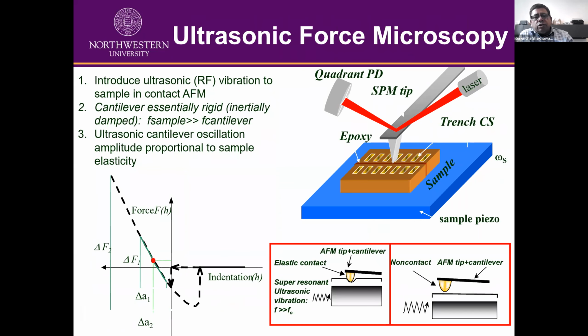Then we also have ultrasonic force microscope. So normally in AFM, you interact with the sample surface, but your indentation is pretty small because of the nature of the tip-sample interactions. So you really will not get that much of the mechanical properties if you have under layers. So how can we understand the mechanical properties if you want to go 10, 15 nanometers below the top layers? If you want to extract some mechanical properties, you cannot do that with the conventional AFM. You have to do nano indentation, but with nano indentation also, you cannot indent 10, 15 nanometers because of the size of the probe.